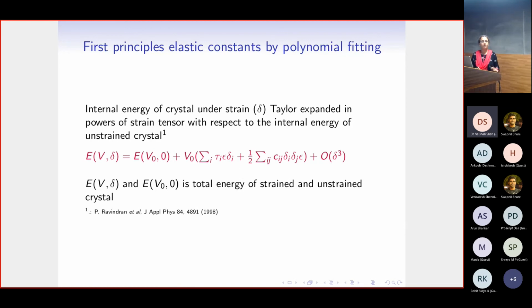And when we initially started working with this module, we realized that the amount of time it was going to require to calculate the elastic constants and give us back the result was going to be a few months. So to get just one set of data for one material, we would have to do the calculation not for a few days or a few weeks, but actually a few months, which means that this was not a viable procedure to work with if we want to work with multi-component systems, because every time I change the composition, I would want to know what are the elastic constants for that composition, and that data should be available to me in a reasonable amount of time. It should not take me 8 months to get a few numbers, right?